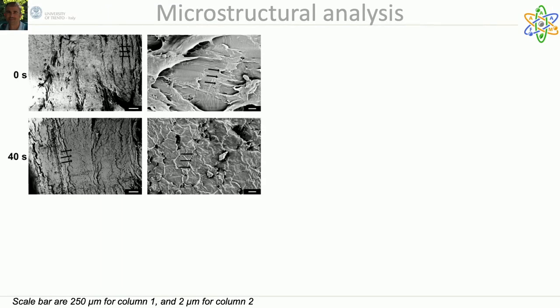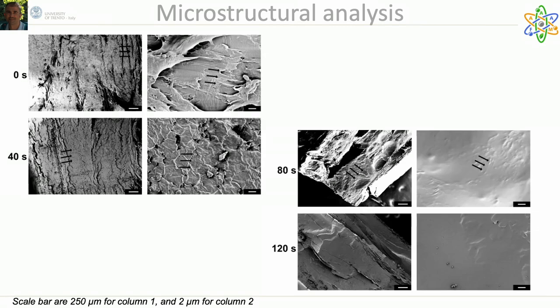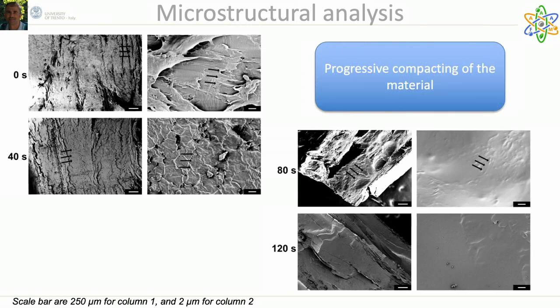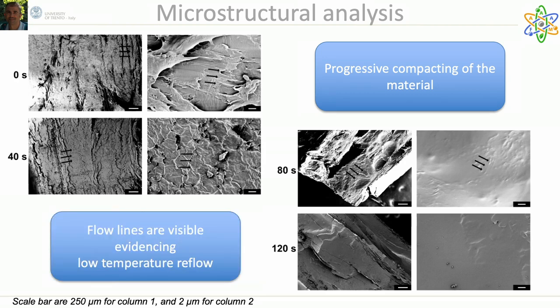The effect of the optimized compression process was also observed by SEM micrographs at different time points: just after the precompression, at 40 seconds and 80 seconds, and at the end of the process, 120 seconds. The black arrows indicate the direction of the compression, detectable from the stratified structure formed during the process. In particular, the pressure planes are perpendicular to the compression direction, with flow lines visible and evidencing low-temperature reflow occurring. These structures can be clearly recognized in the precompressed material and in the first time point at low magnification.